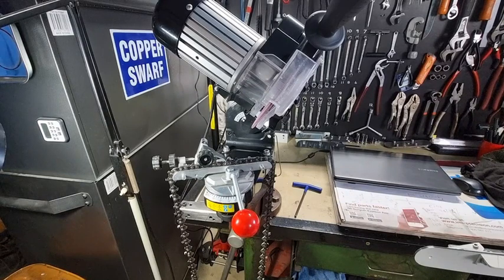But once you go beyond that, and hardening starts, I've got a little bit of a chart here, quite easily obtainable on the internet to download. When we start to get discoloration of metal, we're looking around about 180 degrees, and you'll get a very light yellow at about 180 degrees. So that's not going to do anything. Then you'll be getting up to brown at about 260 degrees. Again, that's not going to do too much. Purple's going to be around about 282, and blue's going to be around about 310.